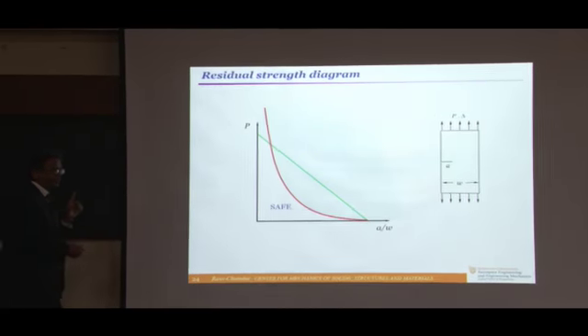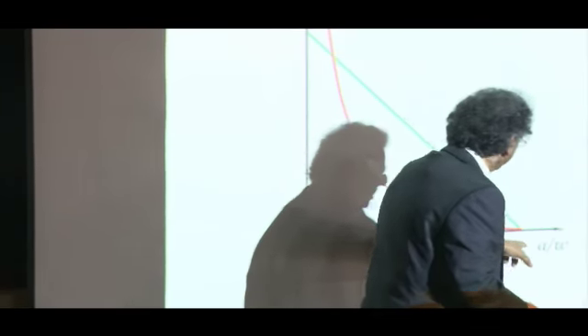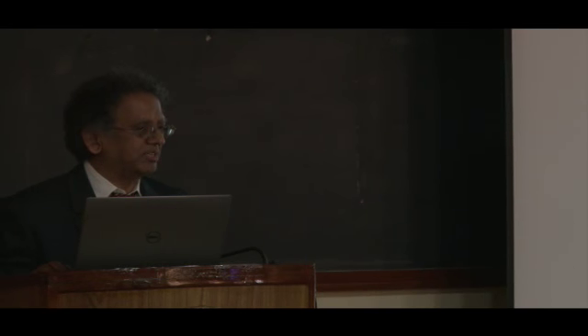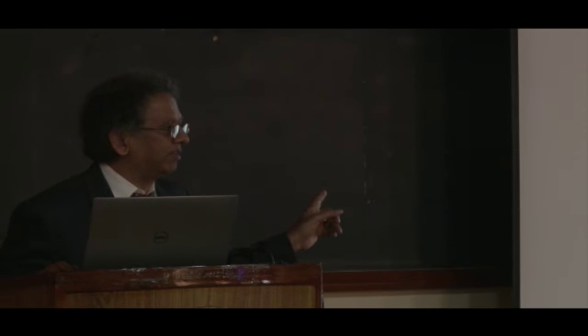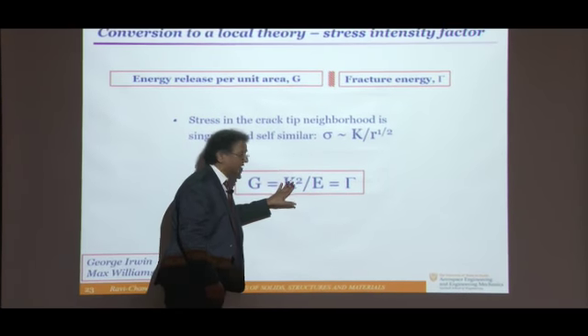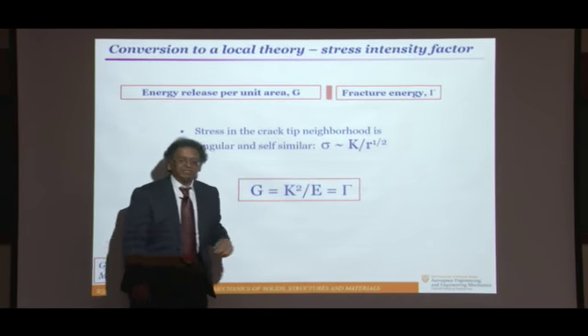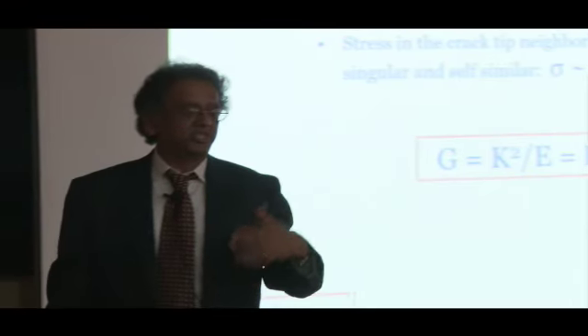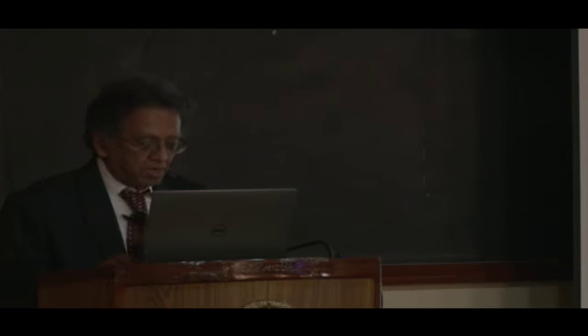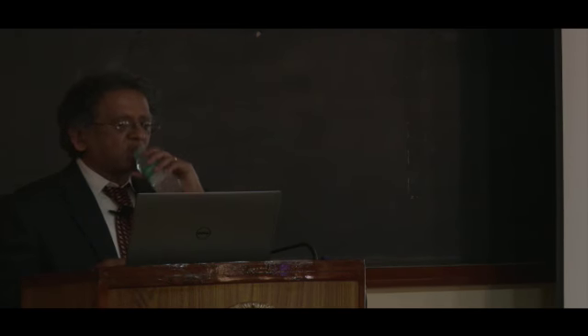So back to this criterion. This is adequate. And if you knew what the fracture energy requirements were, you can calculate when the crack would burn more energy by creating more structure to the fracture process itself. The fracture process starts out somewhere at sub-micron scale when it initiates, but by the time it's ready to branch, it's on the order of 100 microns in diameter. And that's what leads, when the fracture process becomes so large, there are instabilities that set in that create these events of branching or fragmentation.